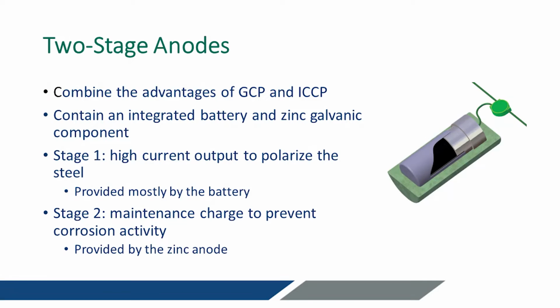So to give you some background, to stop corrosion, you need a lot of energy. But to maintain passivity, once we've stopped corrosion and are in a passive state, we need a little bit of energy to keep it there. I always think of the analogy of friction. I need a lot of energy to get the box moving at the beginning, but once I have that box moving, I need less energy to keep it moving. The same thing in corrosion. Using a battery to discharge a lot of current early, you can passivate the steel very quickly, and then once that steel's passive, you can use a little amount of zinc to maintain that passivity. So it's a much more efficient design.